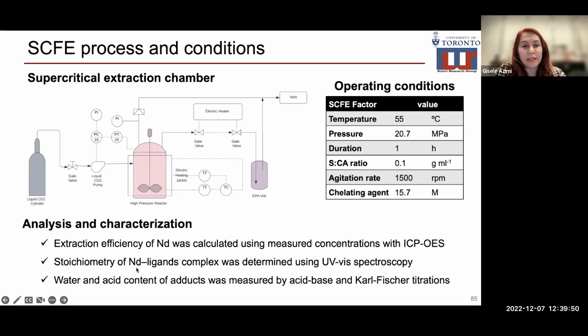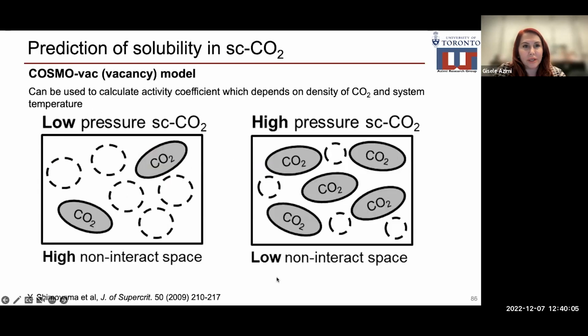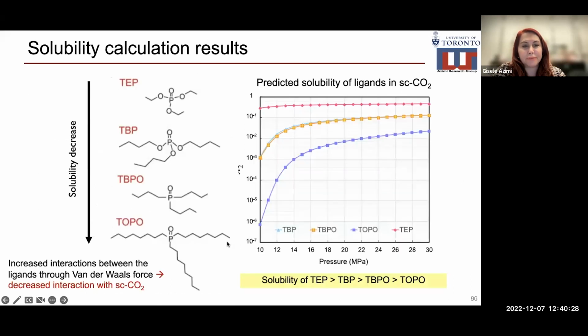We determined the stoichiometry of the neodymium with the ligand complex using UV-vis spectroscopy, and we characterized the ligands for water and acid determination using acid-base titration and Karl Fischer titration. We use COSMO-VAC thermodynamic model to calculate the activity coefficient that depends on the density of CO2 and system temperature. At low pressure supercritical CO2, we have a high non-interact space, and at high pressure supercritical CO2, we have low non-interact space. Here we use this model and we predicted the solubility of these 4 ligands in supercritical CO2. And we see that TEP is more than TBP and TBPO and higher than TOPO.